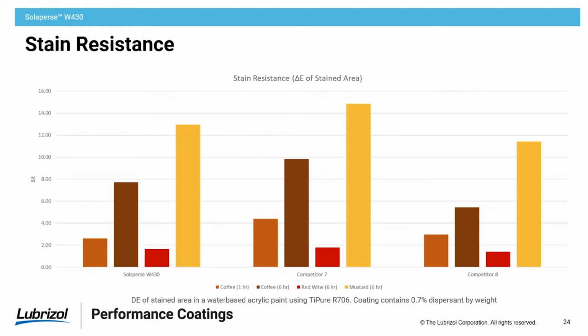And in this testing, we're making a white wood coating using our dispersion of the Ti-Pure 706 that contained on total 0.7% of the dispersants that were being used, including the W430. And what we're looking at is the delta E change between the unstained and the stained coating after the stain has been rubbed off. There's a visual. Really, you can't see much of the stain except in the worst situation. The very, very nasty mustard. Mustard is the bane of the stain resistance test. You really have to have a really high quality system to avoid mustard. Coffee's not looking too good right there either.